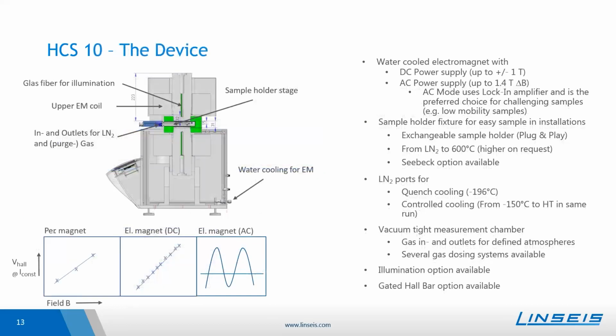So now to the HCS10, the more powerful device. Here you see again a cut through the system, but more simplified. So we also have here the measurement chamber, which can also be vacuum tight for controlled atmospheres. And we also have the liquid nitrogen inlets and outlets for either the quench cooling or the controlled cooling option. Inside the system, we have the electromagnet, which allows either a DC power supply where about 1 Tesla can be applied, or one can use an AC power supply with about 1.4 Tesla difference in magnetic field. And additionally to the AC mode, a lock-in amplifier is needed so that more challenging samples, for example, low mobility samples, can be measured.